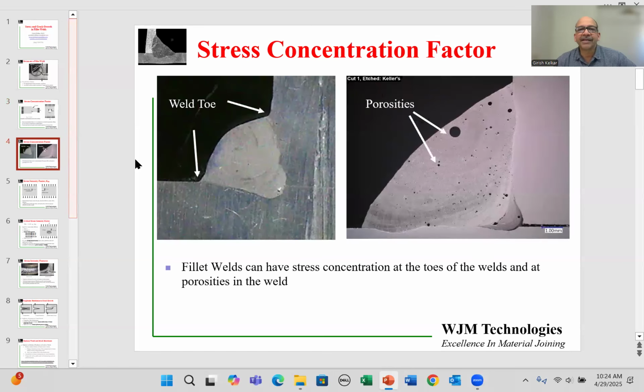And here are some examples of such features. I'm showing you another fillet weld which looks a little bit different than the one I showed before because it has a different surface profile. We'll have the two weld toes, and based on this geometry, there could be a stress concentration effect at the toes. So the stress at the toes could potentially be larger than the overall applied stress on the components.